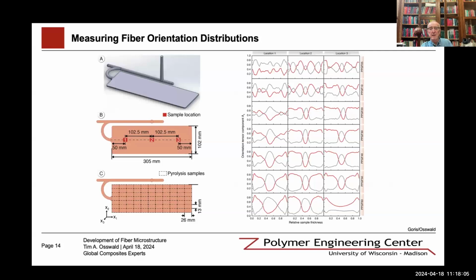So we can do different measurements. So here positions 1, 2, and 3, locations 1, 2, and 3 in the central graph on the left, and there are obviously the measured values, and on the right-hand side with different fiber contents going from 5% fiber content to higher concentrations as we go down. And so you can see the concentration of the fiber affects the final orientation of the part in the different locations. So these are all measured values.